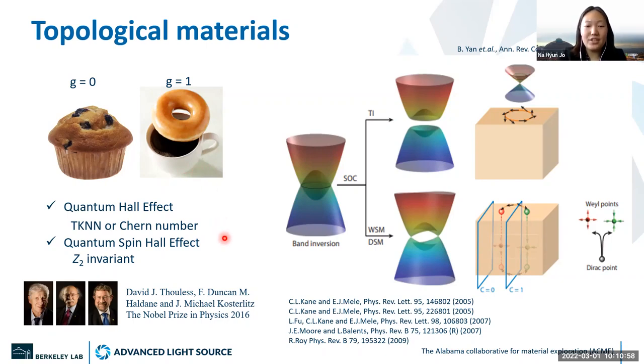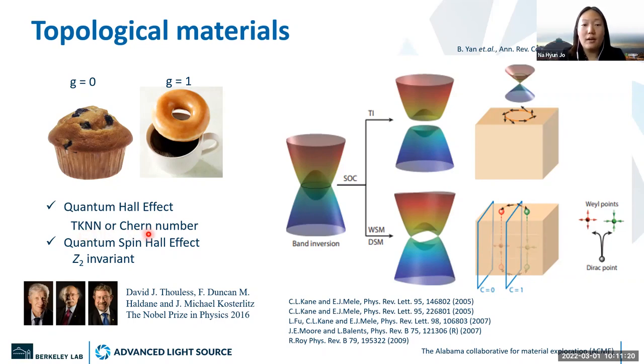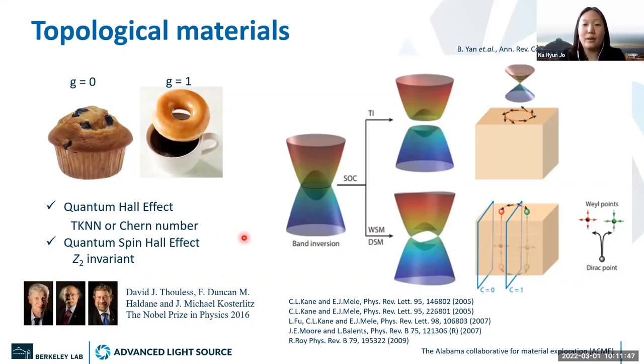This topological concept in real space can also be applied to k-space. The mathematical way of distinguishing topologically trivial from non-trivial states is using a topological index — the TKNN number or Chern number. If we consider spin-orbit coupling, we get the Z2 invariant as a topological index. When the Z2 invariant equals zero, the state is topologically trivial; when it equals one, it is topologically non-trivial. This concept was first predicted from a two-dimensional free electron gas model, but with great theoretical effort, we now know it also applies to three-dimensional materials.